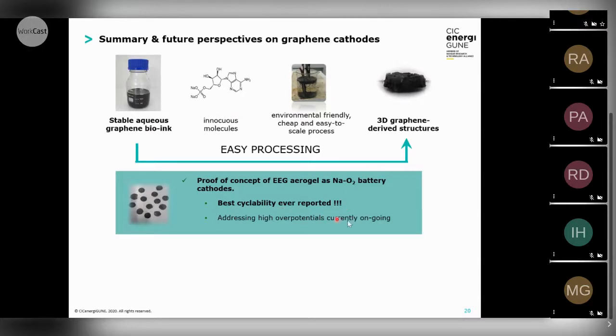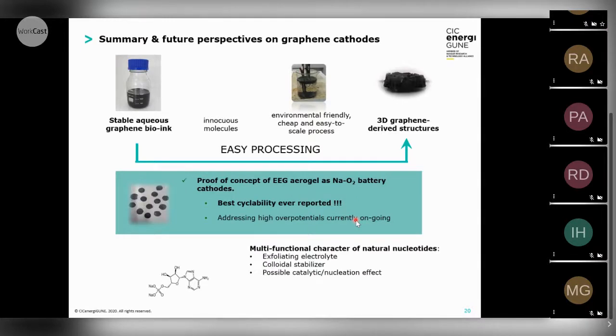And now we are currently addressing this high overpotential with other biomolecules in order to overcome this and to even improve the cycle performance. And also, really important, we have proved the multifunctional character of this nucleotide, acting as exfoliating agent, colloidal stabilizer, and also possible catalytic nucleation effect during oxygen reduction and evolution reaction.